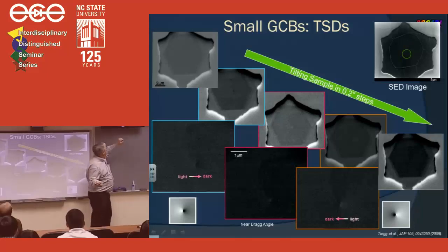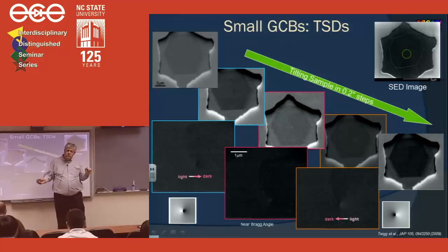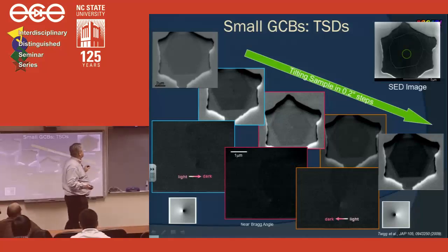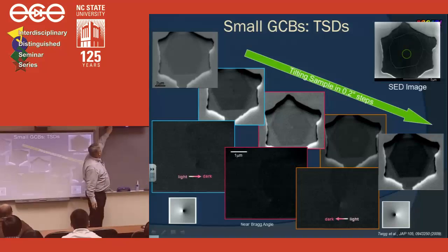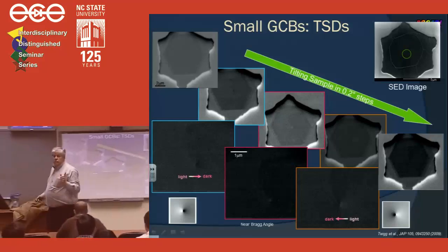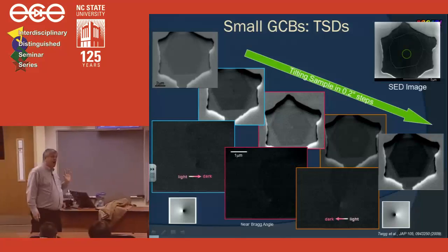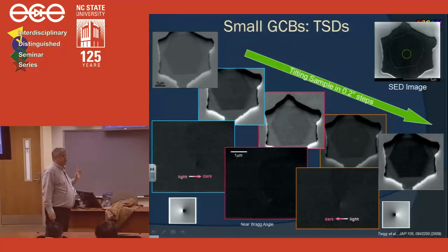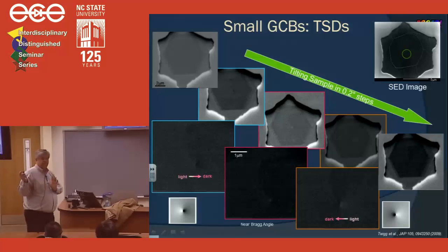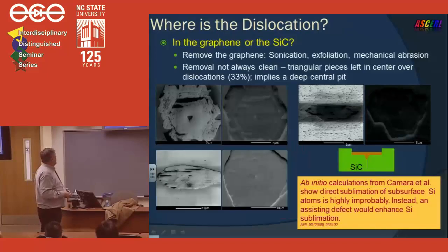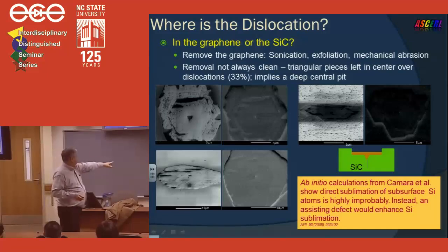Now, Mark Twigg ran the simulation for the SEM under these electron scattering conditions and demonstrated that screw dislocations should show a light to dark pattern and then a dark to light as you pass through the Bragg angle. But only screw dislocations have this behavior. A threading edge dislocation does not show a change in contrast. So this is the smoking gun, that these little pinpoints found at all of these graphene-covered basins are threading screw dislocations. And you can remove the graphene, and after removing the graphene, you still see the little pinpoint in the centers. And I have to tell you, we used an extremely highly advanced technological tool to remove the graphene. It was a Q-tip.